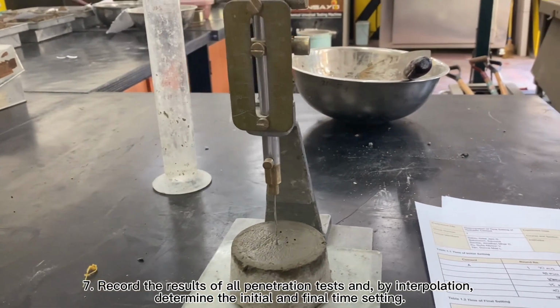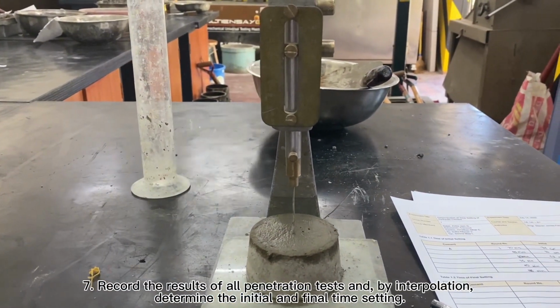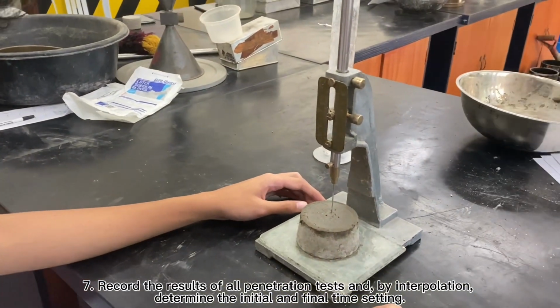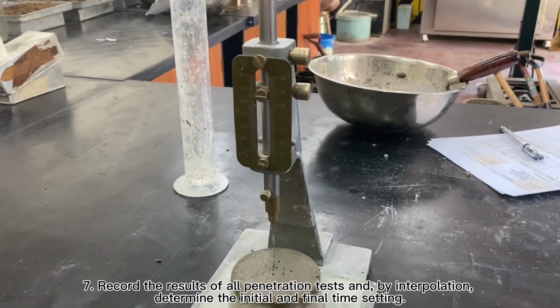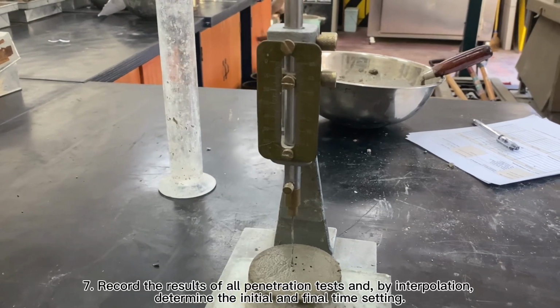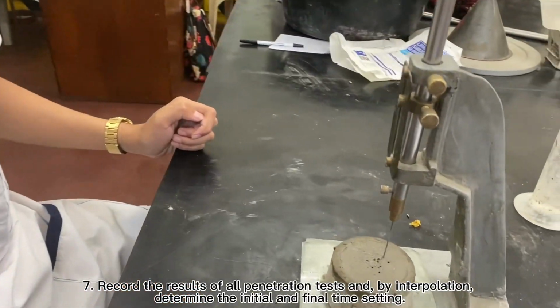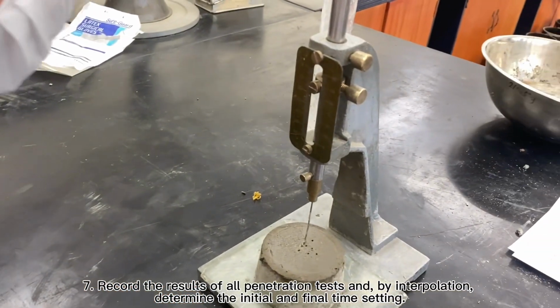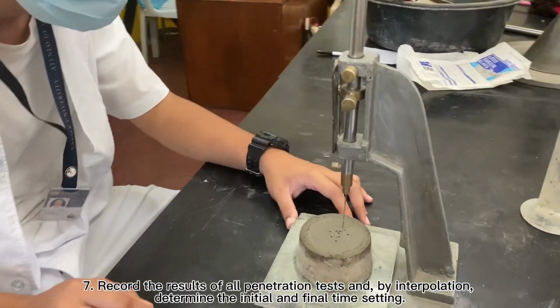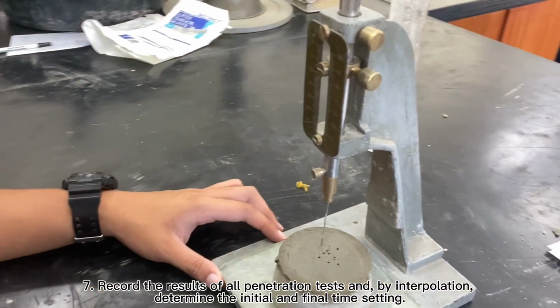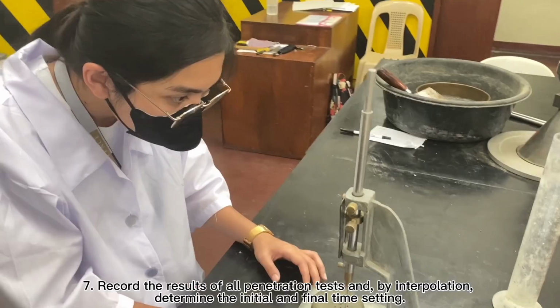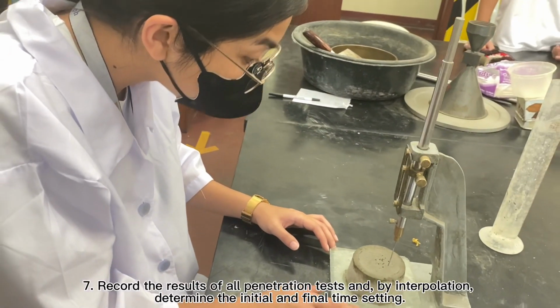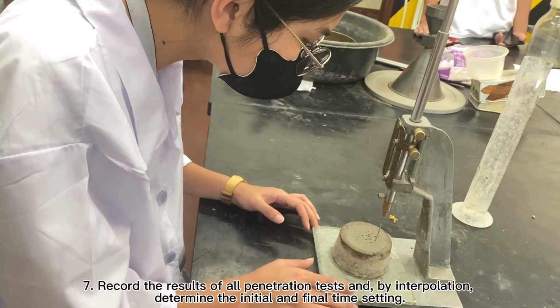Record the results of all penetration tests and by interpolation determine the initial and final time setting. The elapsed time between the initial contact of cement and water and the penetration of 25 mm is the Vicat initial time of setting, while the Vicat final time of setting endpoint is the first penetration measure that does not mark the specimen surface.